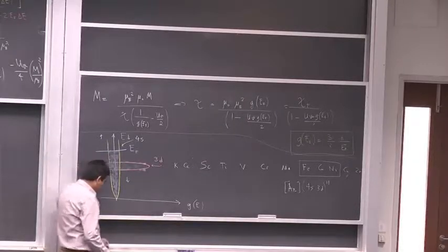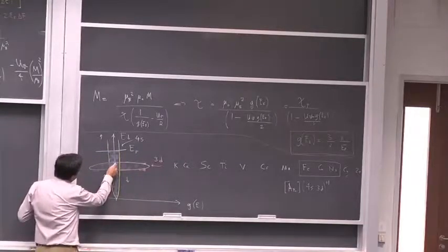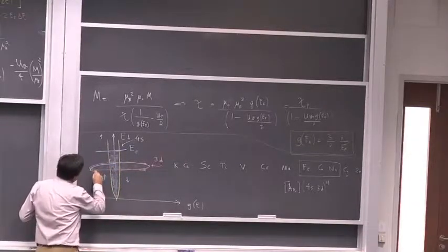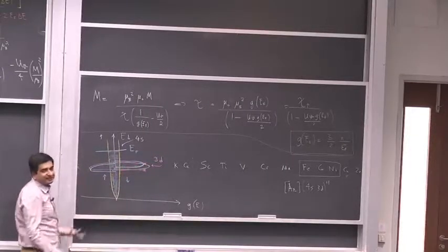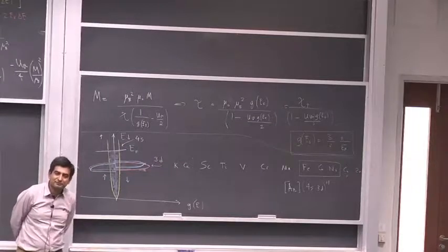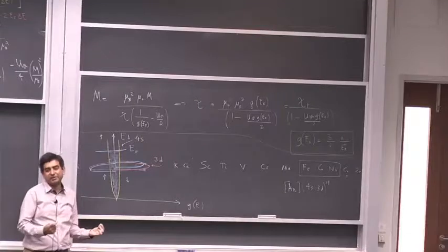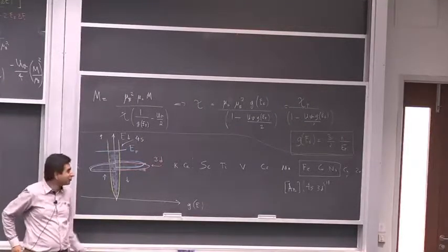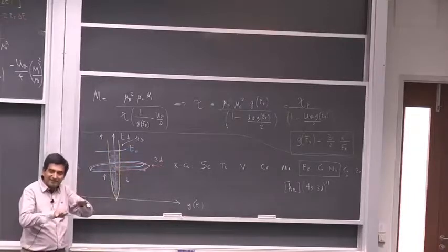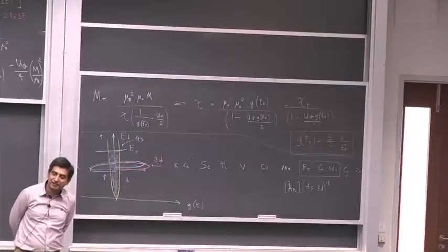So even if there is the Hubbard interaction, which would like to change the position of these bands slightly, nothing is going to change, because you have equal population of spin up and spin down electrons. The sample would not like to magnetize. There is no advantage in shifting the position of these bands through the Hubbard interaction or the exchange interaction. So copper is not a ferromagnet.